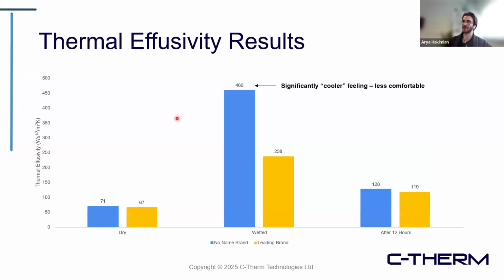But when you go into the wetted state, and this is pre-development of the SOP that we worked on with the University of Alberta, this might have been a little more crude: just saturating the sample and then popping it on the sensor immediately for testing. In either case, it was kept the same for both samples, and we showed that upon initial wetting and then testing, the no-name brand kept things feeling much cooler.